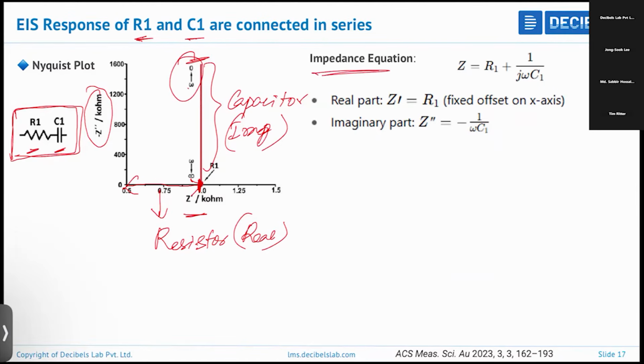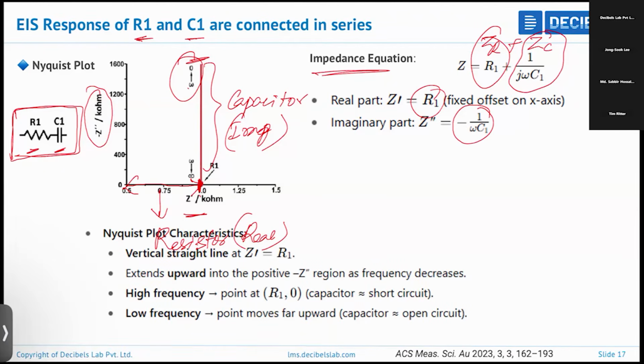So the impedance equation is Z is equal to ZR plus ZC. ZR is R1, and because they are in series, ZC is 1 by j omega C1. So the real part is R1, which is fixed, and the imaginary part, Z double prime, corresponds to the capacitive impedance, that is minus 1 by omega C1. The vertical straight line at Z prime is equal to R1, and it extends upward into the positive minus Z double prime region as frequency decreases. Here this is high frequency, omega is equal to infinity, here omega is equal to 0.